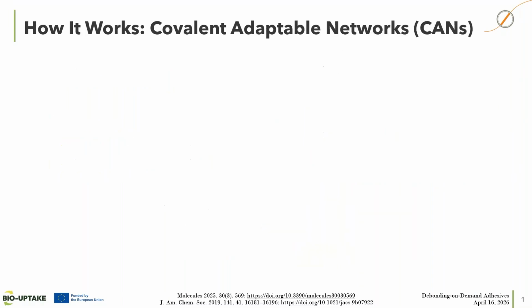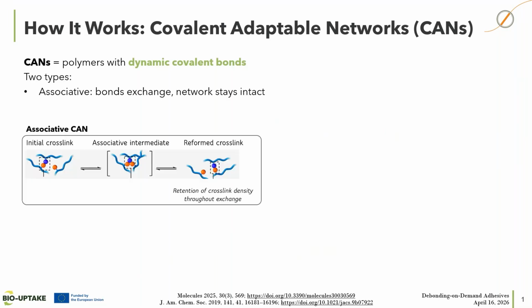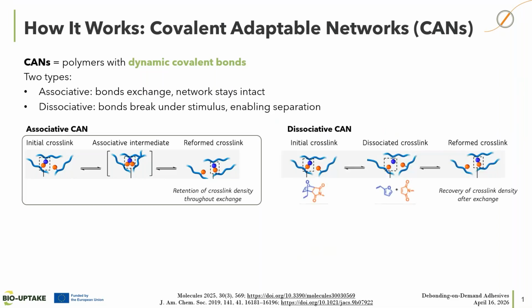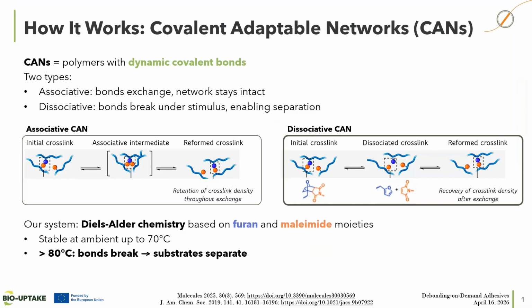So the key mechanism behind our system is based on covalent adaptable networks, or CANs. So CANs are polymers with dynamic covalent bonds. That means that the network can reorganize under certain conditions. So there are two main types of CANs. The associative ones, where the bonds exchange upon activation, but the cross-link density remains intact all along the process. And the dissociative CANs, where bonds break upon activation, which enables the debonding. Our system uses the dissociative approach, which is ideal for a clean separation.